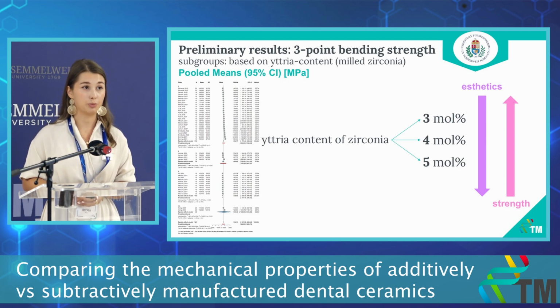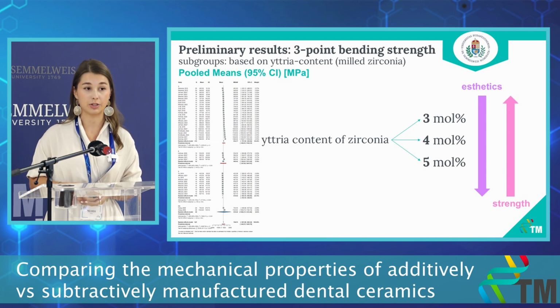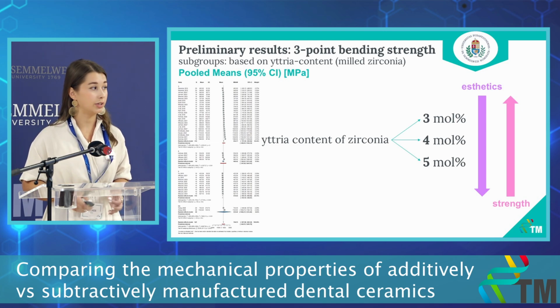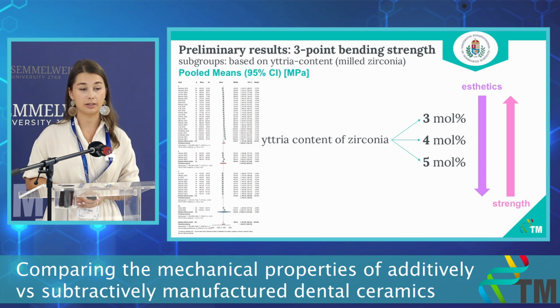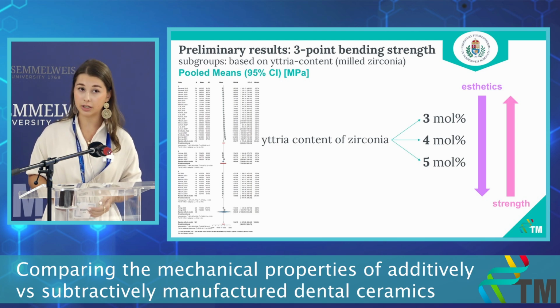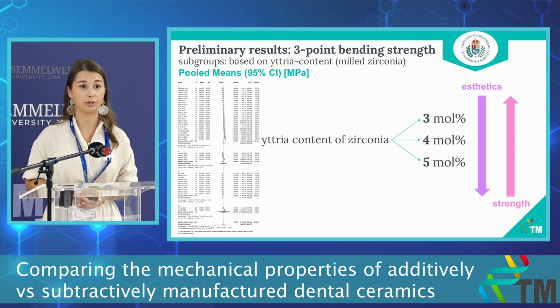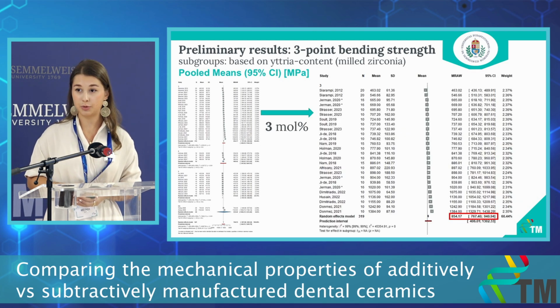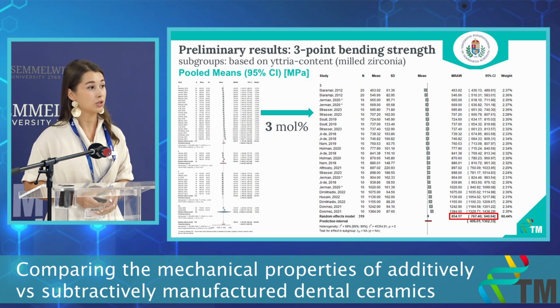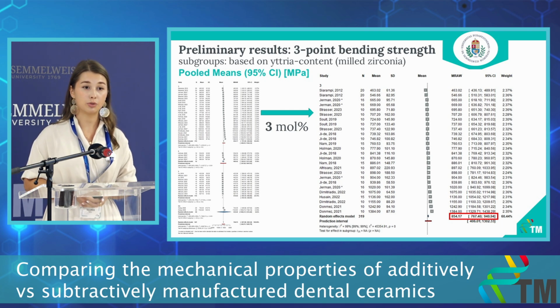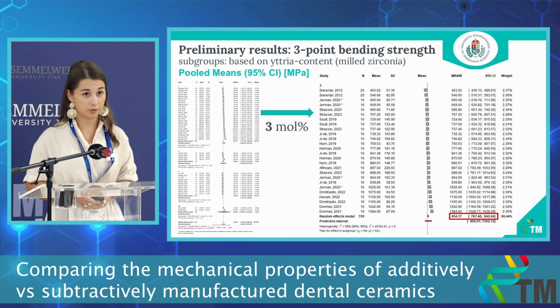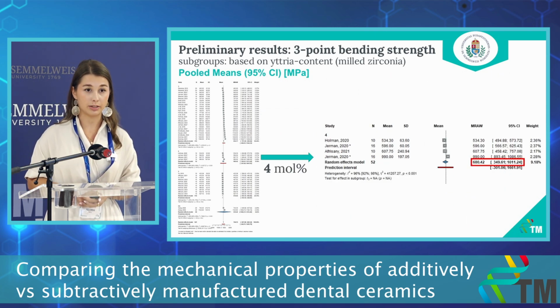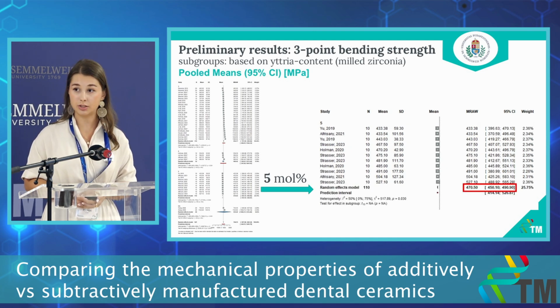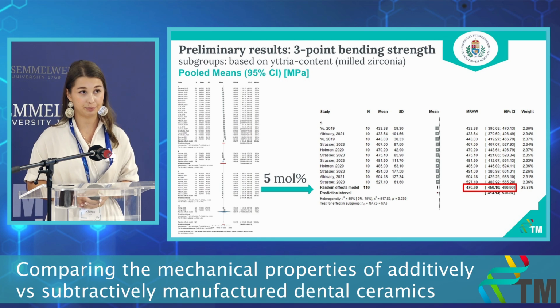Here we conducted a subgroup analysis based on the yttria content of zirconia. Zirconia has usually 3 to 5% yttria in it, and to put it simple, the more the yttria, the better the aesthetics, but the weaker the material. Looking at each subgroup, we can see the recently mentioned pattern, which is already well known in literature. So with 3% yttria, we have an overall flexural strength of 850 megapascals. With 4% yttria, it is only 680 megapascals, and with 5%, it decreases to 470 megapascals.